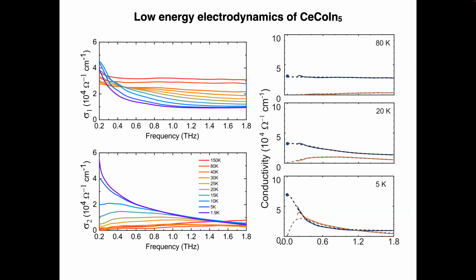That's what conductivity curves look like. So we have the real and the imaginary parts of the conductivity, sigma 1 and sigma 2. At low frequencies, so that's the low temperature curve here, 2 Kelvin, it's very non-Drude-like. You have a peak that is maybe Lorentzian, but then there's this long tail, right? Cerium cobalt indium 5 is a complicated system, and we wouldn't expect a pure Drude-like response. We measure the real and imaginary parts, but there is an appreciable part of the low temperature spectrum which has a peak, which carries a lot of the spectral weight of the conductivity.